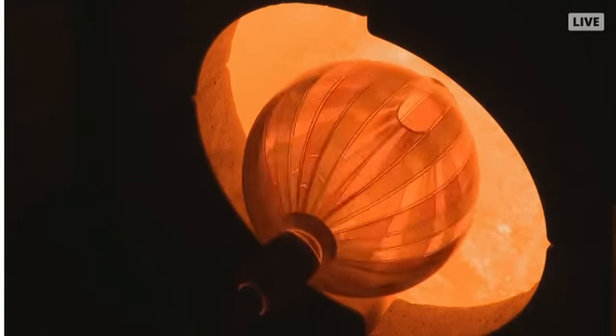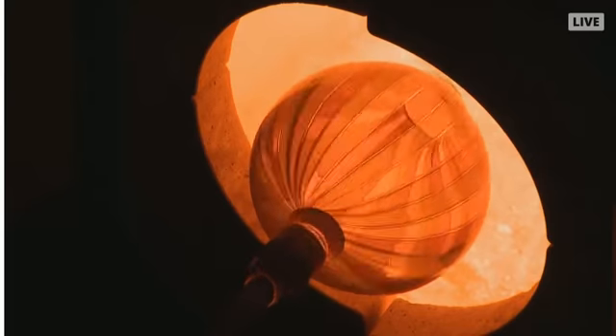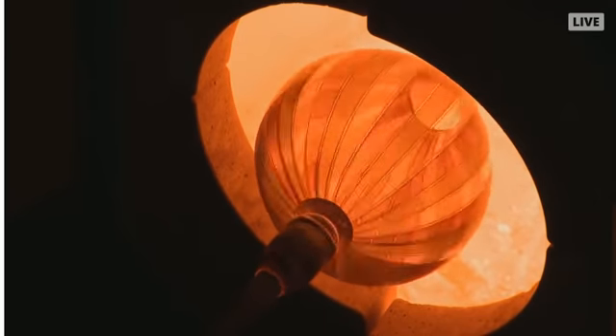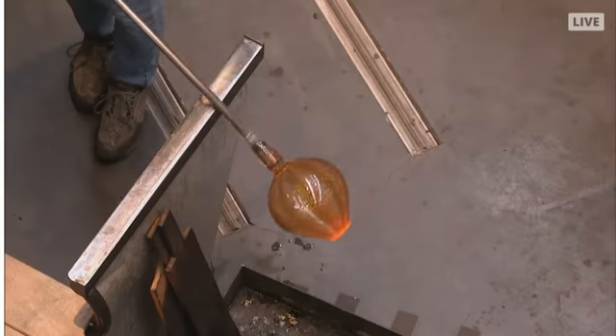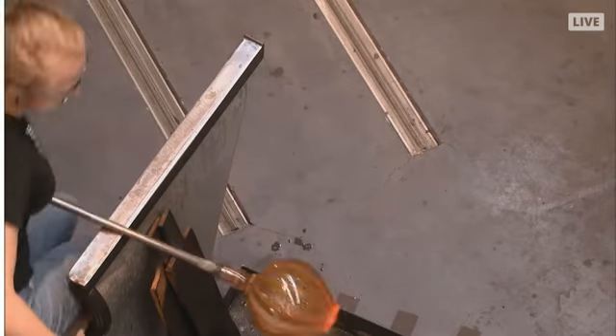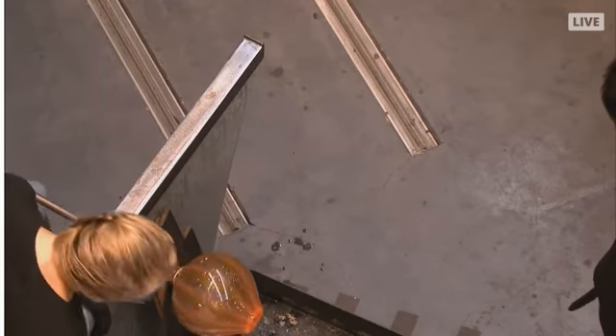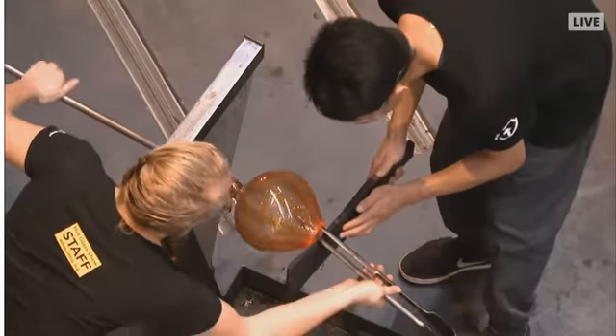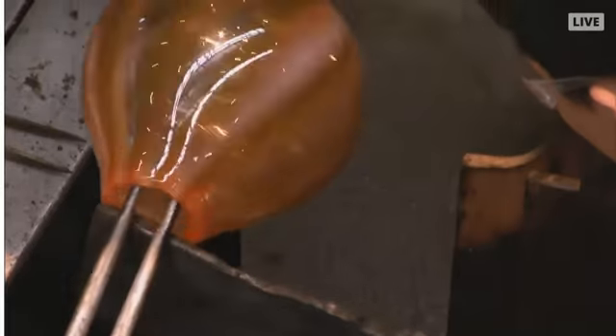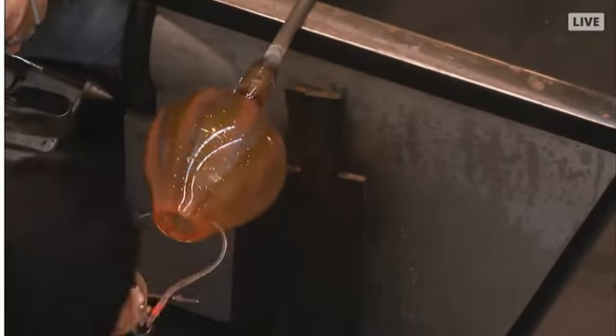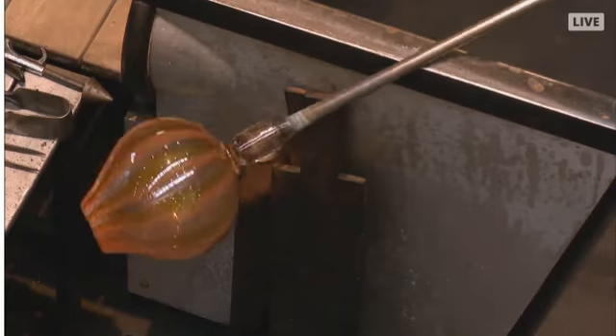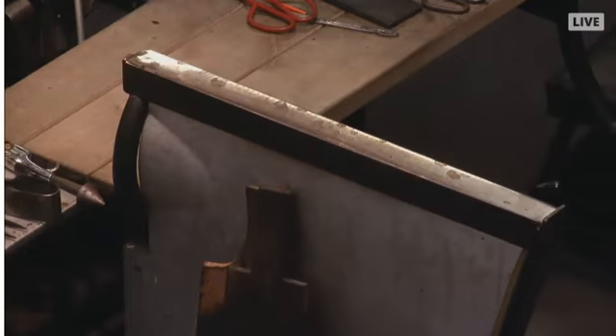And again, that basket is at a very precarious temperature range. It's in the pickup box right there, and it's at right about 1,000 degrees. Now, if that pickup box is at, say, 1,100 degrees, that basket in there would stick to the floor of the box and it would slump over. If it's at 900 degrees, or even 950 degrees, if we pick it out of that box, it'll cool down too much by the time we make it to the furnace, and it will break when you put it into the furnace. So we've determined that for our pickup box here, it has to be just over 1,000 degrees. And at that temperature, we can pick it up and get it into the furnace, and we're pretty sure that it won't break. So we'll see how this all comes together here.